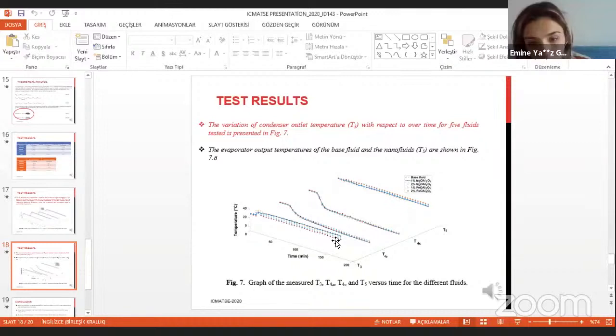But unfortunately, in literature, it says that temperature 3, which is the condenser outlet temperature, needs to be lower if we want a high coefficient of performance. At temperature 5, we have the evaporator output temperature, and in here it needs to be higher for the higher coefficient of performance. So we want temperature 5 higher, and in here the nanofluids have higher values, we can see.